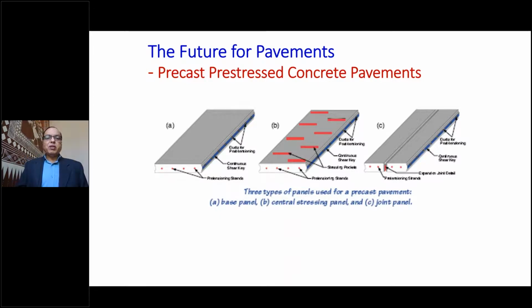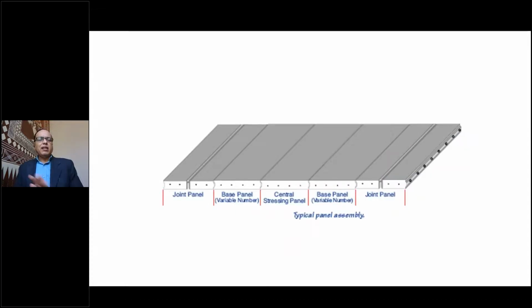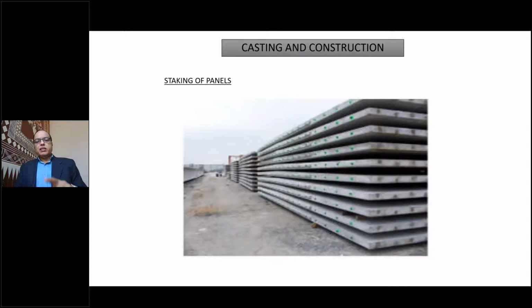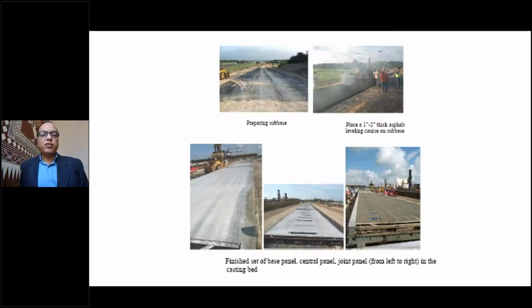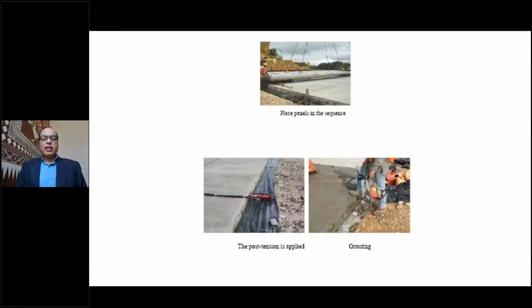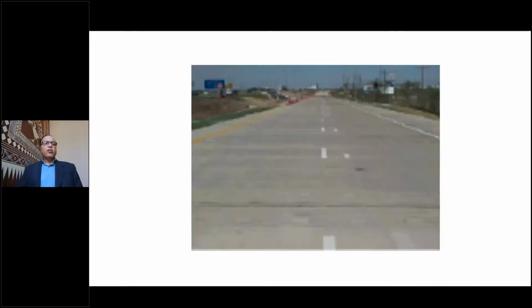In precast, pre-stressed pavements, the different panels are designed and cast at site. You can see that these precast panels are already made and kept on either side of the road. The road is operating, but these precast panels are already kept. Then the road is closed to traffic. This is the case of a road which was closed to traffic in the evening, and the subbase was finished and the panels were laid, and then the joints were finished, and the road was open in about 12 hours' time. The next day morning, the road was open to traffic.